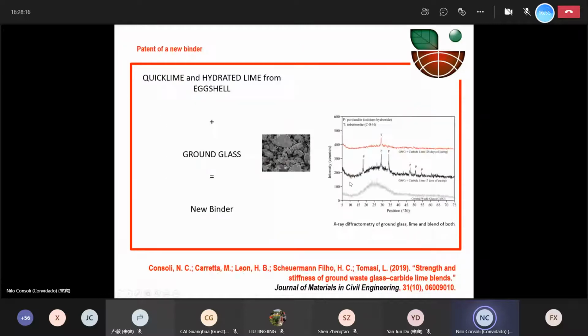But even more interesting than that, we got a patent of a new binder. It was mixing the eggshell with ground glass. Both were residues, and so we have had a new binder that was possible. We can see here in the X-ray diffractometry the formation of a new cement, which forms tobermorite, which is also formed if you use Portland cement, for example. This was specifically a paper from 2019, also in the Journal of Materials in Civil Engineering.